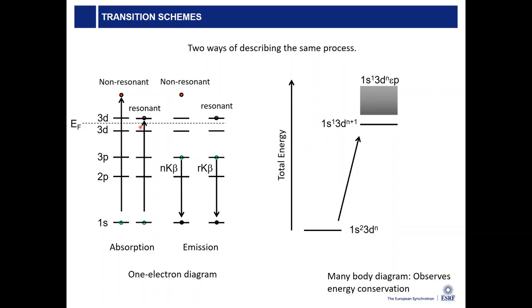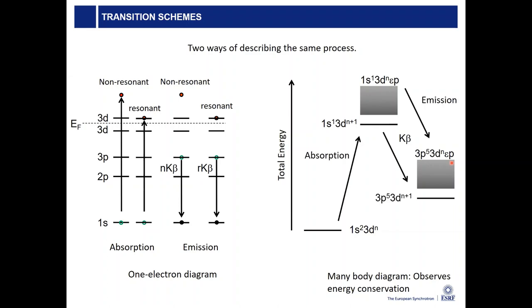That would be the resonant excitation, where I excite a 1s electron into a 3d orbital, and I reach a configuration 1s1, 3d n plus 1. So again, this is a multi-electron description of this excited state that I reach after this resonant excitation. And if I now want to describe my K beta lines, in this case this is a non-resonant K beta line, I replace a 1s hole with a 3p hole, and this electron just stays up there. So this is this red electron there. It just stays in its epsilon p state or orbital. Then the resonant emission, this is the case shown here with the excited electron staying in the resonant shell, goes down to this state there. And so this is the many-body description of the same process.